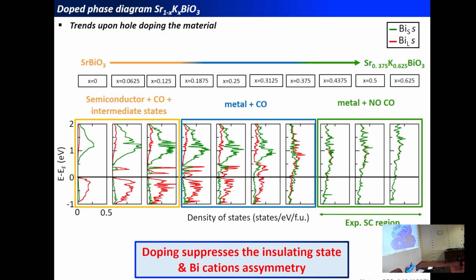So we have the bipolaron there. It's localized in the band gap. That's what we expect for a semiconductor. But then when you put more and more, you close the gap. It's not anymore a semiconductor. But yet there is still the asymmetry in the electronic structure, meaning that very likely there is still a charge ordering in the compound. And then if you sufficiently substitute strontium by potassium, the asymmetry disappears, and so the two types of bismuth cations are becoming very similar.